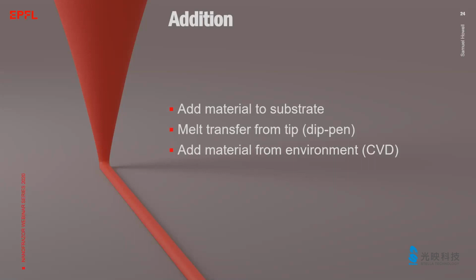During our literature research, we found one publication that used a heated tip for local chemical vapor deposition to deposit copper and copper oxide nanostructures. So here, a precursor is collected from the gas phase, from the environment, and solidified through a chemical reaction on the substrate. And one can also imagine that the tip can be used to locally dope material under the tip with a suitable dopant from the gas phase. So here, many possibilities are yet unexplored.